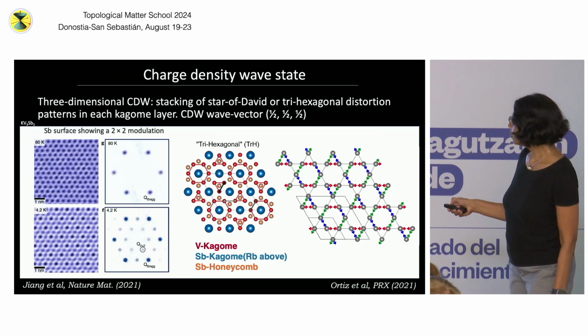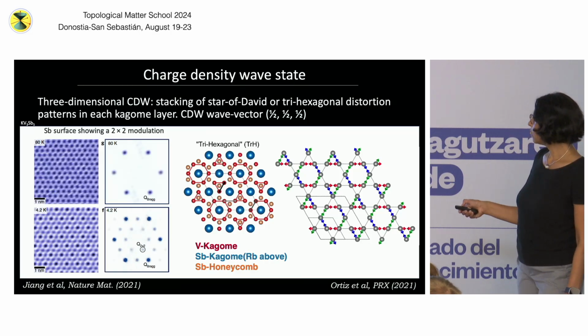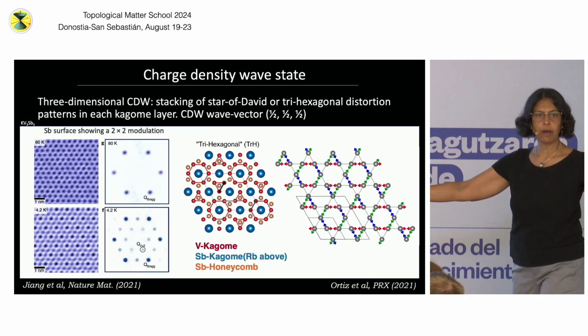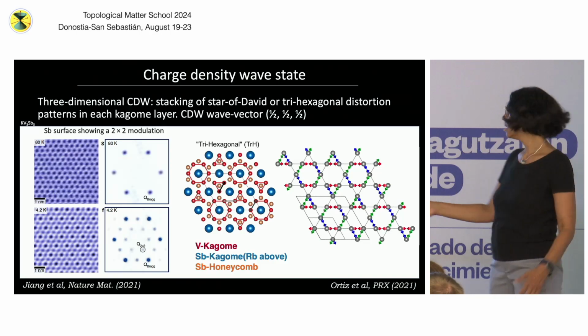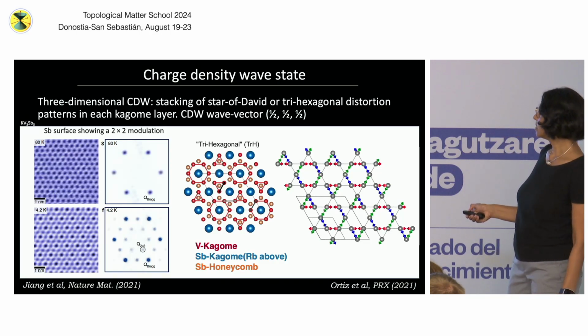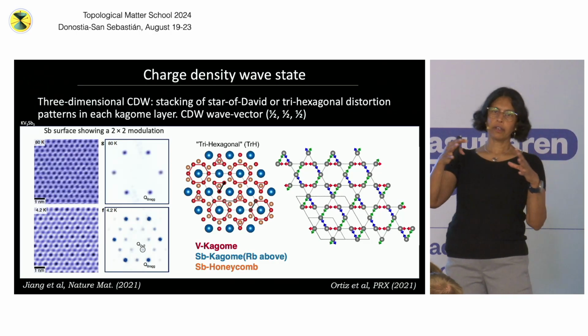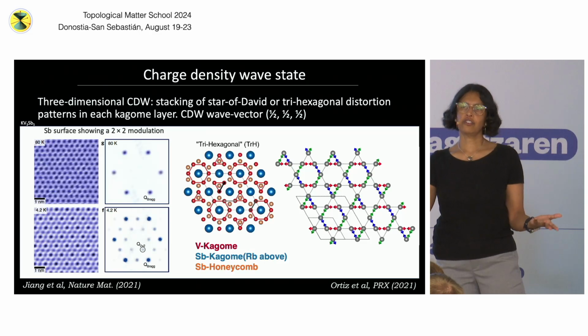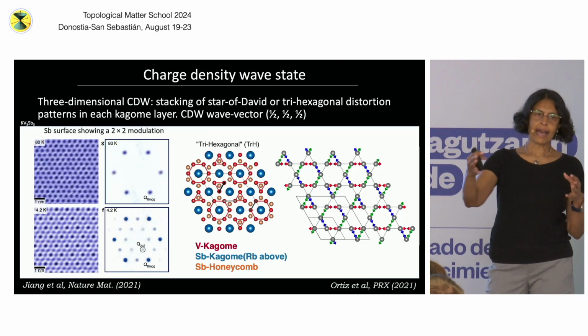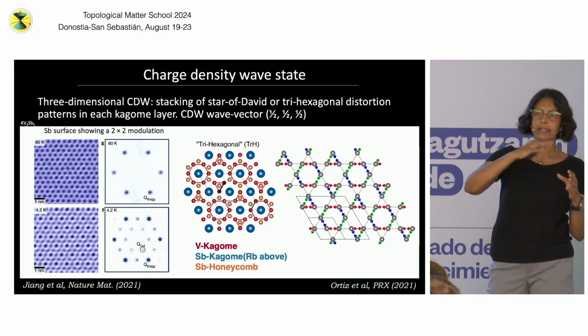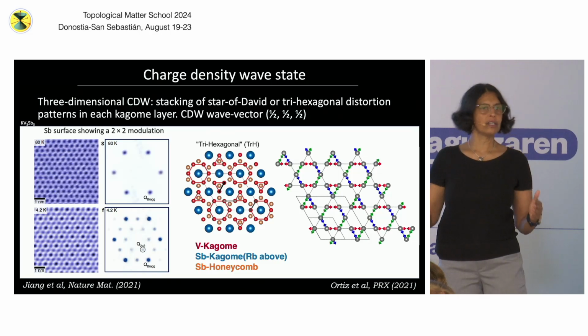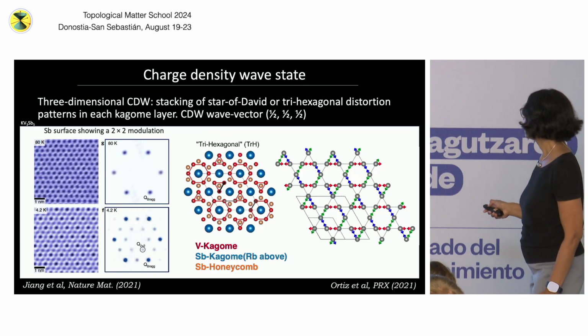And then you go to low temperatures, below the CDW transition. You get additional peaks, 1, 2, 3, 4, 5, 6. They're at a smaller Q, that means larger real space periodicity. This is a 2x2 charge density wave, so the size of the unit cell in real space is just doubling. So every second atom it's bright, dark, bright, dark, bright, dark in 3 directions. That's the charge density wave.